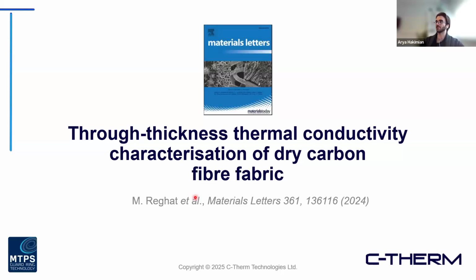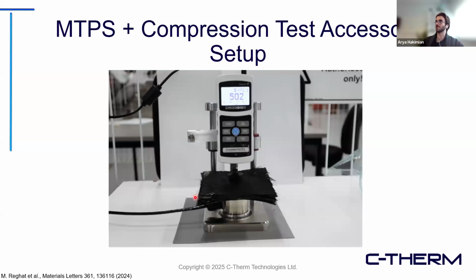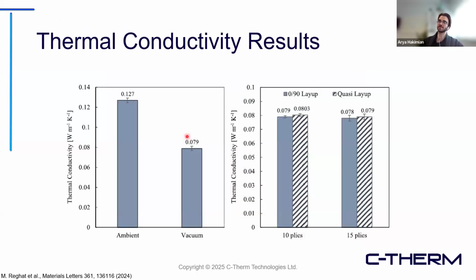The next one here is titled Through Thickness Thermal Conductivity Characterization of Dry Carbon Fiber Fabrics. So again, this was a recent publication from last year using the MTPS. Again, this one was really purely focused around the conductivity side of things, but they're looking at these types of carbon fibers in their materials. So in the paper here, you can see a nice little picture of the setup that was used. This is, again, that CTA, compression test accessory. We have the MTPS below it here, and then the different carbon fibers that they were looking to assess the performance of. When we look at the data set, they actually did some interesting things here.